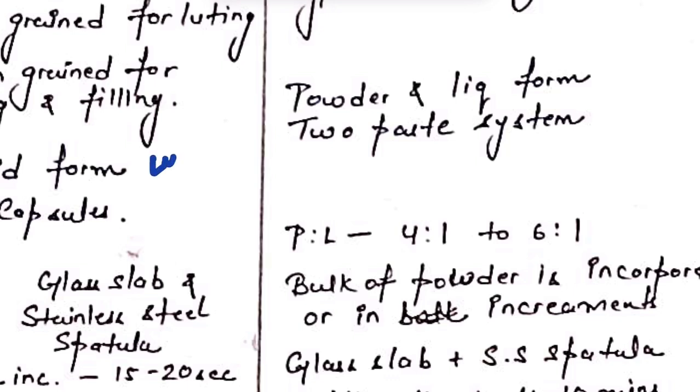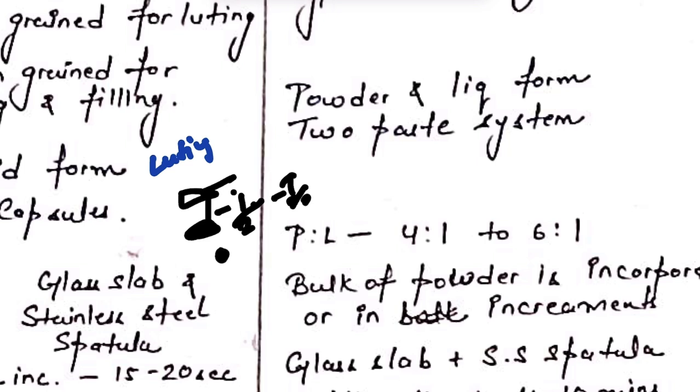What you will see, when you have your spatula, right? Let's say you have your mixture over here and you have your spatula. So when you lift your spatula from the mixture, you will see strings of about half to 1 inch forming, okay? So about half to 1 inch long strings of the cement will be formed. You will learn this in the practical manipulation as well, okay? And for base consistency, you should be able to make a stiff dough, okay? You should be able to make a dough of this entire mixture. So that is about the manipulation, okay?